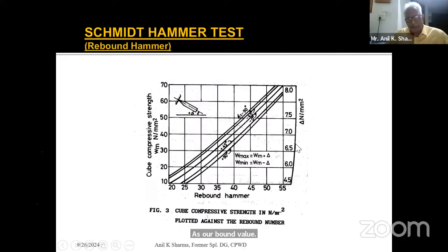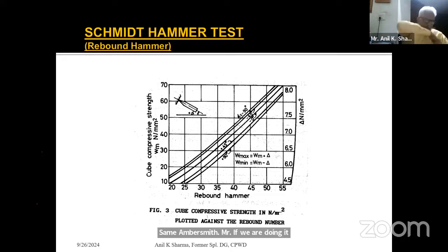And using these charts, even though these charts are giving the strength of the concrete, depending upon the angle of inclination of the rebound hammer, if we are using it for the slab from below, then the rebound value will be different. Same Schmidt hammer, if we are doing it from top in the reverse direction at 180 degrees, then the rebound value will be different. So these rebound values are corrected using the angle of inclination of the rebound hammer from the surface of the concrete. For example, plus 90 degrees, plus 45 degrees, 0 degrees, minus 45 degrees and minus 90 degrees. If we are using it horizontally on columns, then the rebound value for the same hardness of the concrete will be different. So this is how these rebound values can be interpreted using these charts.